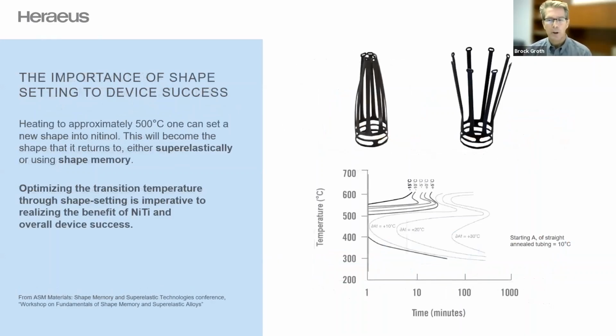In the interest of time, we're going to go very quickly on this slide. What I'm going to say is there's a range of temperatures that you can use to shape set your device, and that will affect the transition temperature of the device. So at the top on the right, you've got a shape set, kind of conical shape. On the left is what that device looks like coming off the laser cutter. The tines or the legs curl in and kind of touch one another, and that's just residual stress in the tubing or heat affected zone, things like that. That's not a problem. You can shape set it as you need, but in doing this shape setting, you've got these in the lower right hand, this graph, you've got some very unusual curves.